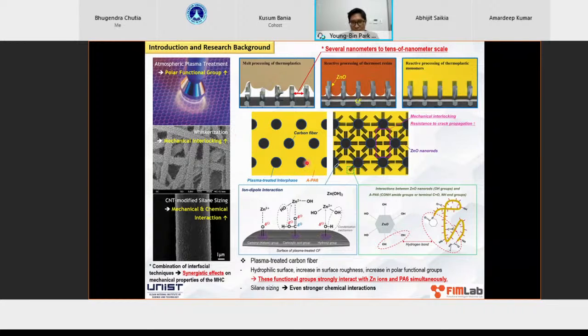And as I said before, as you can see on these two comparative schematics, on the left-hand figure you see the black carbon fibers without any surface treatment, without any whiskerization. And after whiskerization, you see these nanorods vertically grown on the surface of carbon fiber, and they create mechanical interlocking, which leads to enhancement in the mechanical properties of the composite.